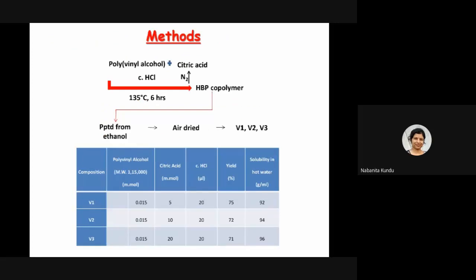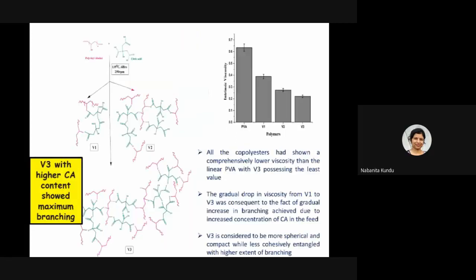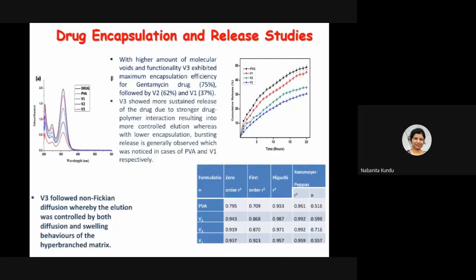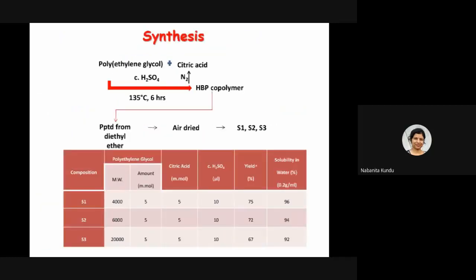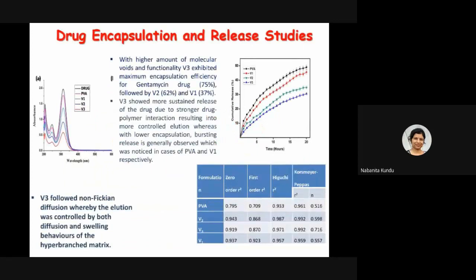So we have actually used very simple monomers to start with. We have used polyvinyl alcohol and citric acid. You know that citric acid, citrates, are very good antimicrobial agents, meaning they can act on the microbes to kill them. So we started with citric acid and polyvinyl alcohol, and we formed this kind of hyperbranch structure, and we characterized it using NMR, IR, viscosity and all, and we established the hyperbranch structure, right? And then we applied it as a therapeutic agent, as a drug release agent.